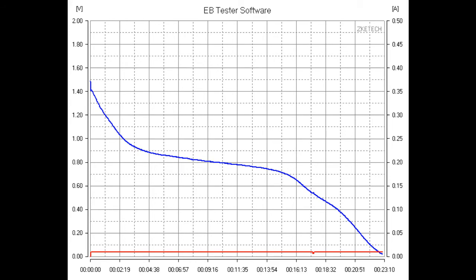This is the best I've managed so far for a zinc-ion battery in terms of energy density. I have also tried adding just a conductive additive — graphite — to the sodium vanadate without my sugar carbon foam, and it doesn't perform as well. I believe adding an activated carbon like this can give better results for zinc-ion batteries, and I think I've read somewhere that this has been proven.